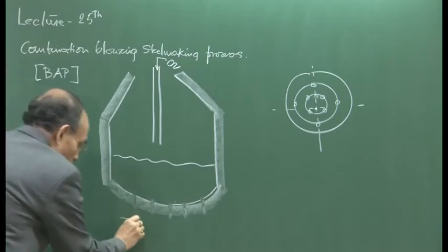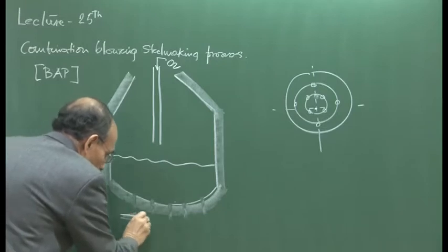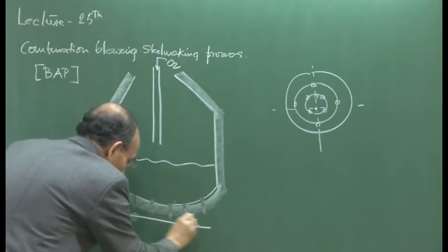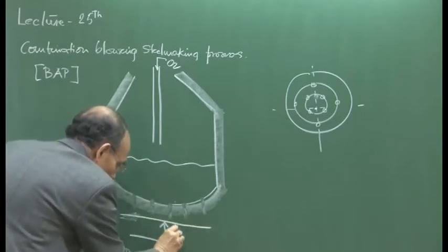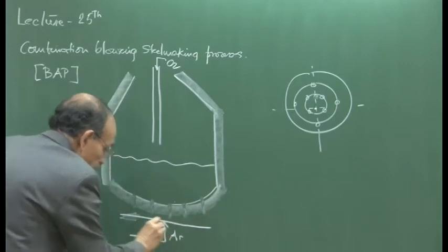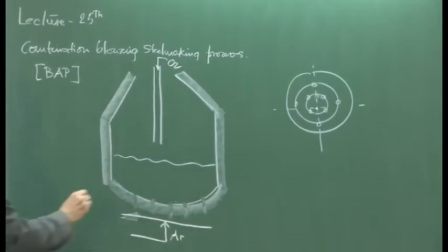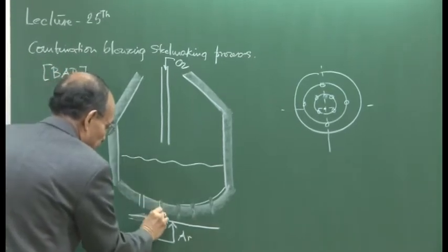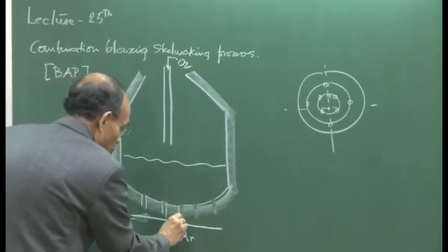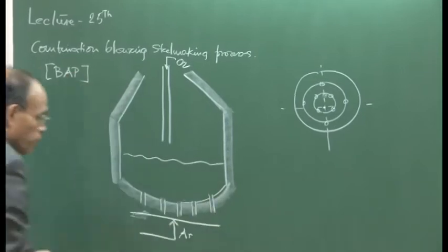A little bit of argon — say 2 to 3 percent by volume of the top gas — if that could be introduced through the porous plug, can dramatically improve the characteristics of the process itself.